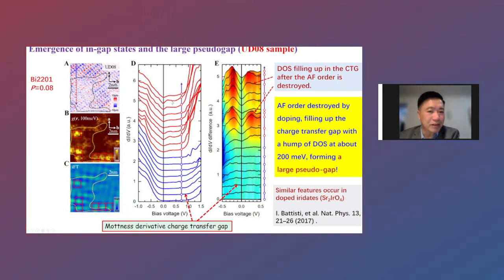So you can see this kind of hump. This is due to the quasi-particle density of states through the doping. If we use this line as a background to subtract all the curves, then you will see that once you go to the region without anti-ferromagnetic order, you see this kind of density of states piling up in this charge transfer gap, which forms a so-called large pseudo gap with energy about 200 meV. There is a hump here, okay, so this is a quasi-particle doped into the anti-ferromagnetic order in the Mott gap, charge transfer gap, to form this kind of density of states.